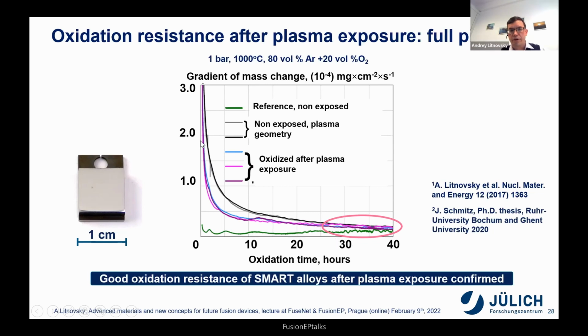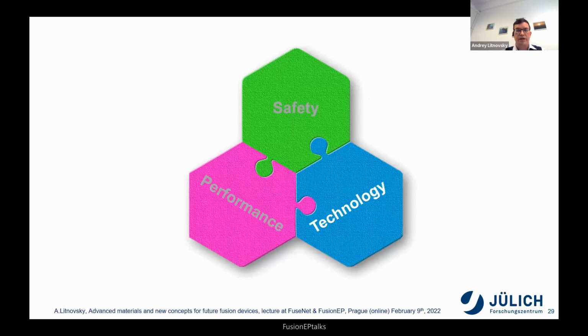The material is good. The shape is what governs this change of mass, which is simply the burning out of dirt from the manufacturing of these samples. But the material as such works well irrespective of plasma prehistory. This was a very important result.